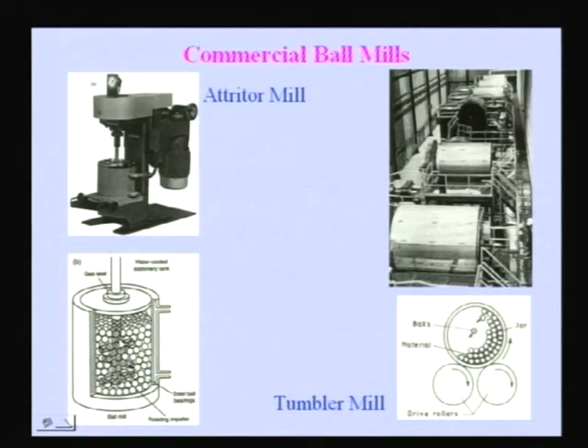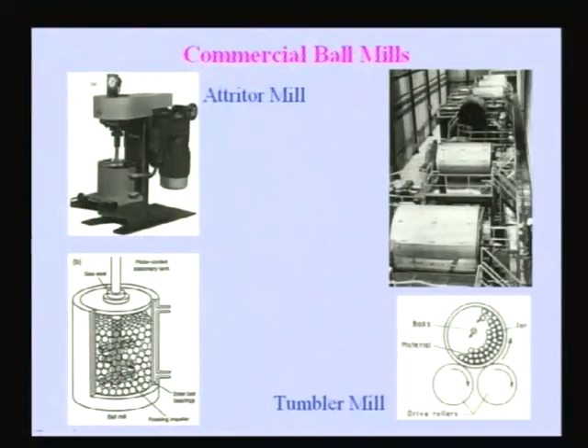So, here instead of a drill bit, what you do is to that shaft you put some horizontal rods which are called impellers. You put horizontal rods to that shaft and then put a container here. This is a container, and that container consists of the balls and the powder. And so, when you are rotating this shaft, the impellers also move, and once the impeller hits a ball, that ball goes and in turn it hits a powder particle. There is a probability that a ball will hit a powder particle. At the same time there is also a probability that the ball will hit another ball. So, some energy is lost between ball to ball interactions, but at the same time some of the energy also is transferred to the powder. So, as a result you get some transfer of the energy, and finally the powders get converted to either nanocrystals or quasicrystals or intermetallics or amorphous phases or anything that you are interested, depending on the total energy that is transferred. So, this is one type, and here you can in principle go up to about 5 kilos.